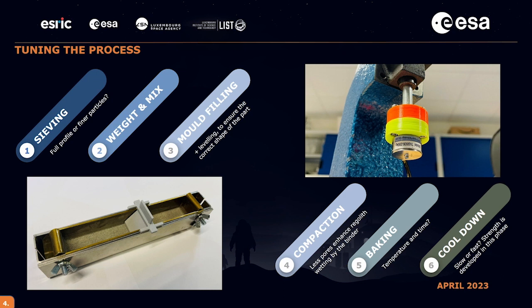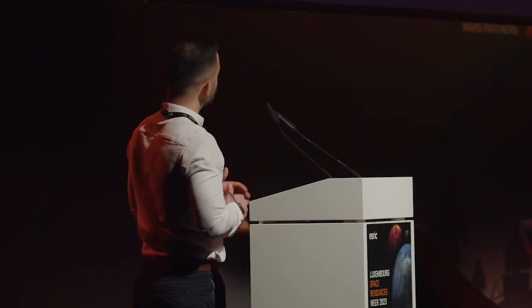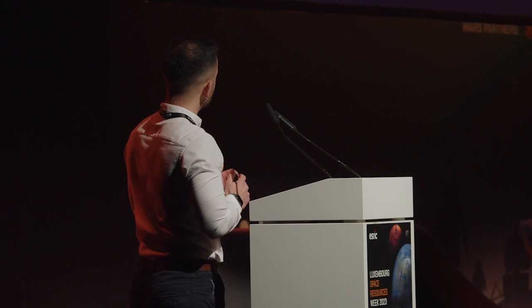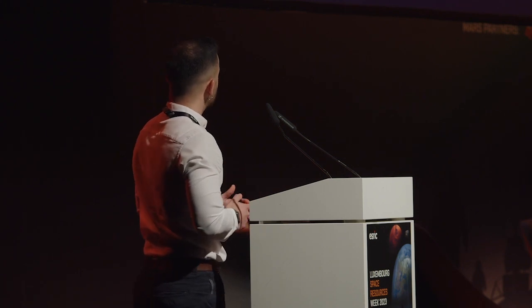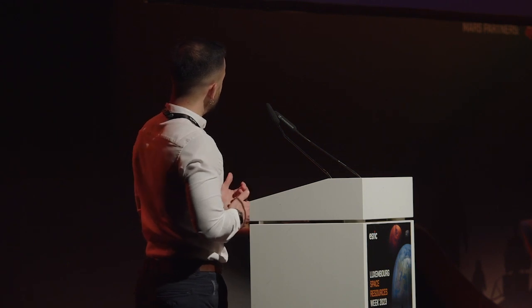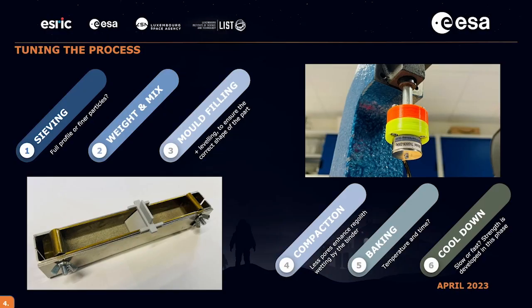Then we need to fill the mold. In this step, the third one, it's really important to make the powders flat, because they are not going to, let's say, flow once we compact them. The compaction, of course, is very important because it's the step in which we enhance the possibility of the binder to wet the regolith later. And as you can see in the picture on your right, we did this with a hand press equipped with a 200 kilogram load cell, which gives you already the idea of the low pressures we were using.